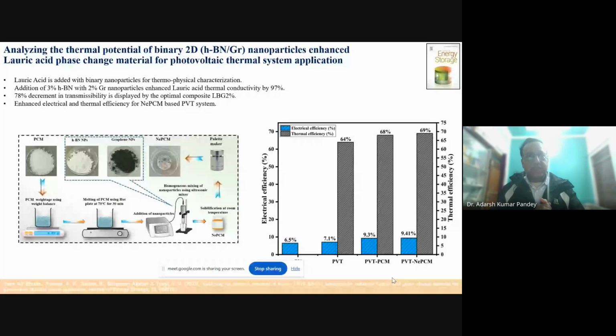In this nano-enhanced phase change materials work, we not only studied the eutectic and the single nanoparticles, but also the combination of these two, meaning a hybrid of nanoparticles. We have done the hybrid of hBN nanoparticles and graphene nanoparticles, a binary kind of nanoparticle study, with boron nitride added to lauric acid. We added 3% of hBN and 2% of graphene nanoparticles, and the thermal conductivity was enhanced by 97%. Further, the absorbance was enhanced.